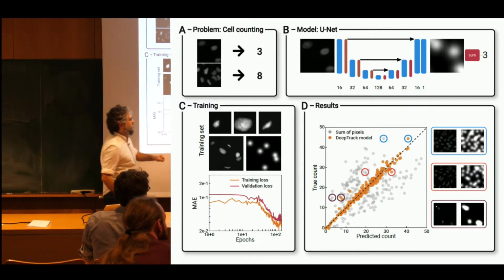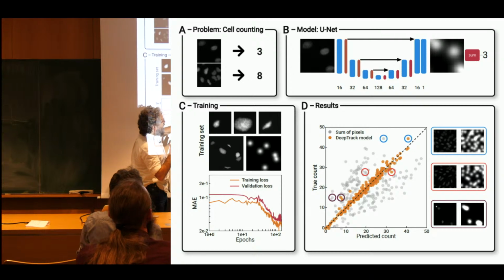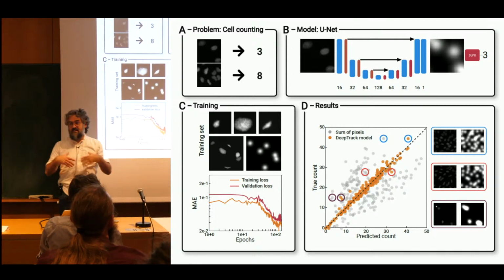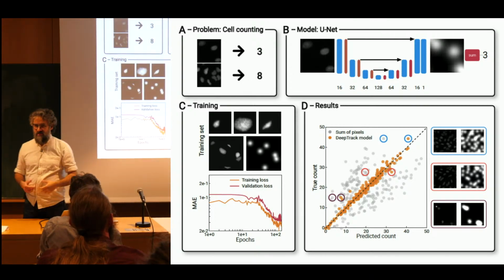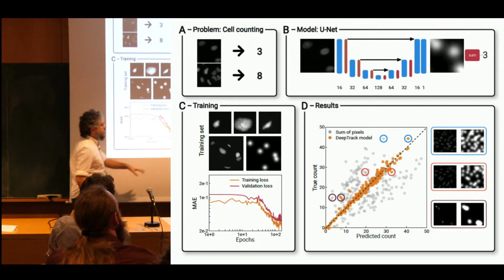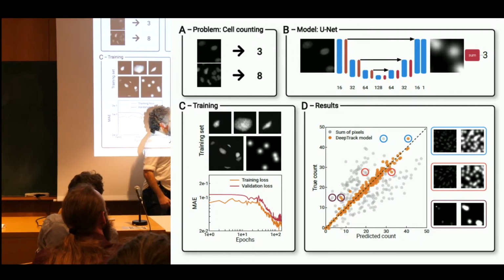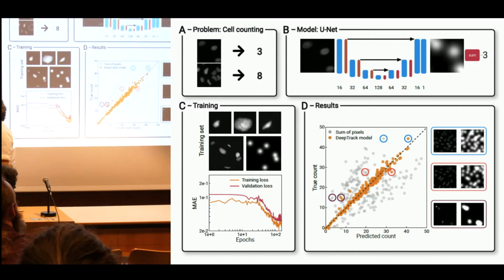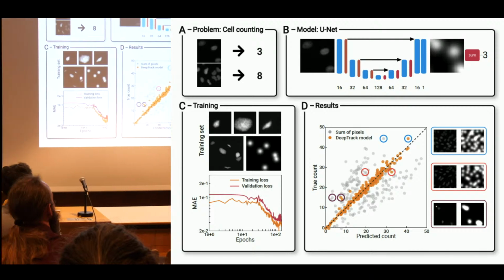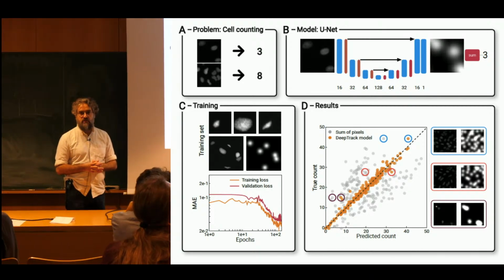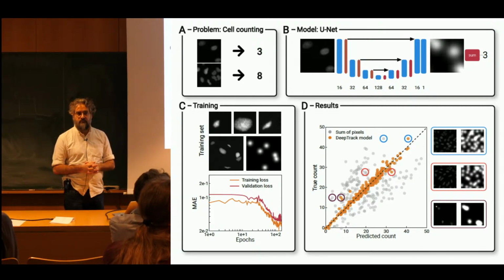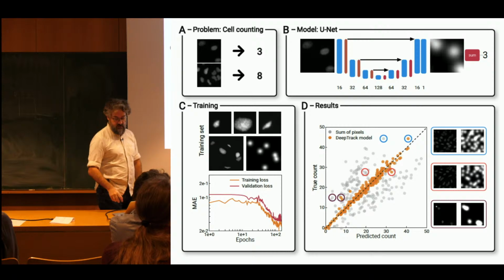That's the true count. And of course, you can argue, yes, but you could just take the total intensity of the original image, and then what do you get? Well, if you do that, you get this gray result in the background, which is still correlated with the number of cells, but not as well as what the neural network can do. So it's actually an improvement over that.